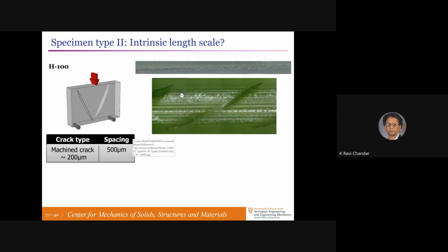Parent crack is in the background. This is the width of the parent crack. These were cut with a saw, so they have a certain dimension to them. It's on the order of 200 microns or so. They pop these daughter cracks. These are the daughter cracks.